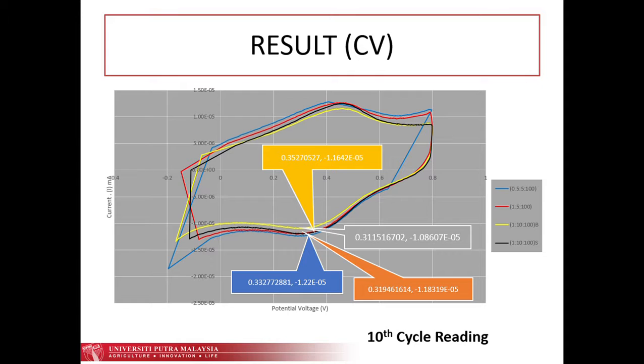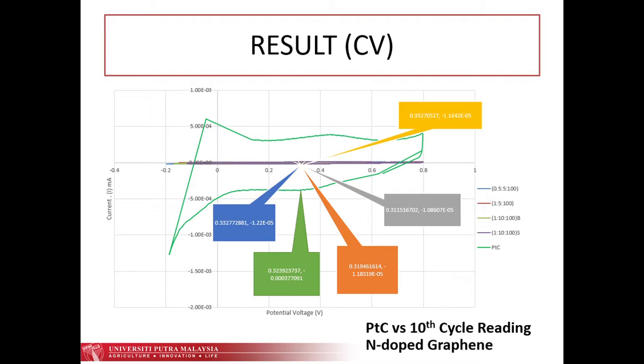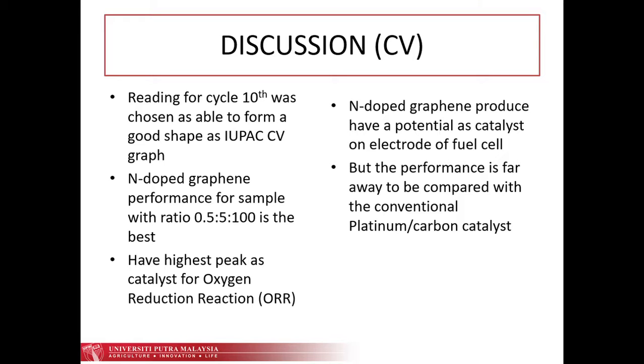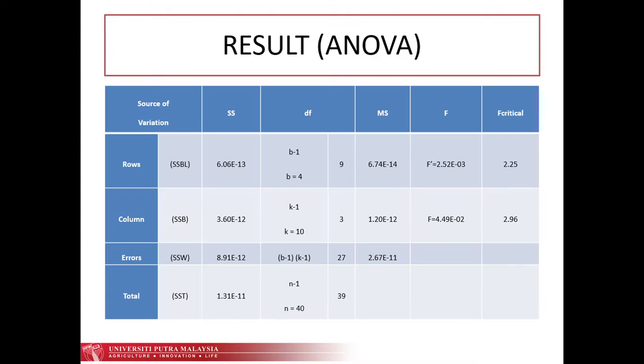And this is the result for the cyclic voltammetry. We compare the four samples, and from the 4 samples, it shows that sample 2, with ratio 0.5 to 5 to 100, which is 0.5 gram of graphite, 5 grams of melamine, and 100 grams of ball mill balls, has the best result for the ORR. We also compared the result with the conventional platinum carbon, and we can conclude that the nitrogen-doped graphene has potential as a catalyst, but the performance is far from comparable to the conventional platinum carbon catalyst.